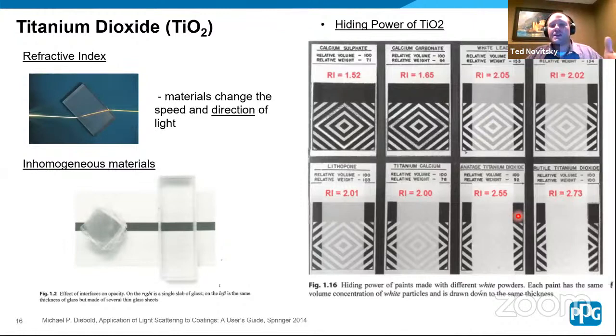And the main reason is because it's inhomogeneous, like this example here, and it's about the difference between the refractive index of the polymer and the refractive index of the titanium dioxide. So the more different they are, the more that light is bouncing in and out and at different angles, and it just makes for good scattering, which we know that scattering makes something white. So this is why titanium dioxide is so important to paints, along with the fact that people just really like light colors.